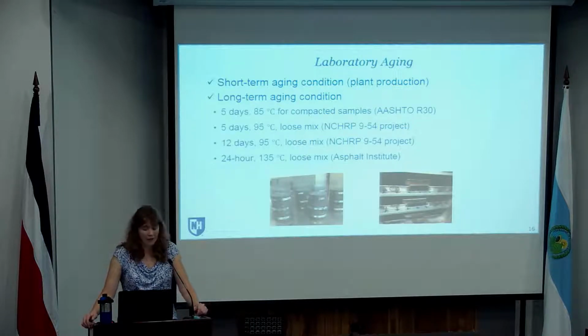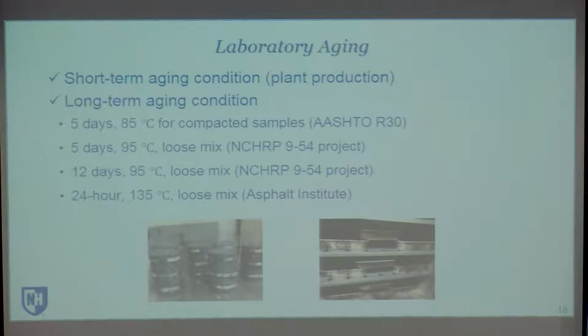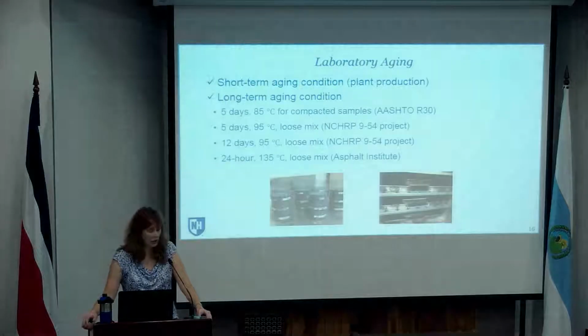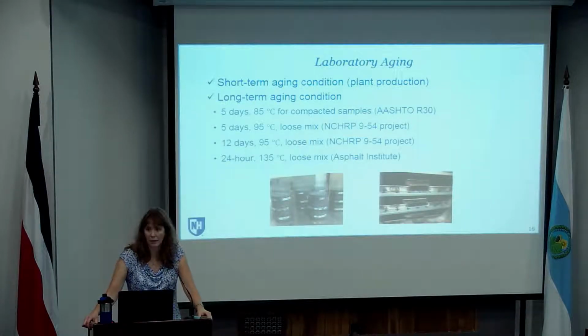So we looked at 5 days at 85 degrees C for compacted samples, which is the current recommendation through AASHTO R30. We're looking at both the 5 and 12-day 95 degrees C on the loose mix, which is coming out of the NCHRP 9-54 project that was recently completed. And then we also looked at 24 hours at 135 degrees aging on the loose mix that was coming out of Asphalt Institute recommendations. So we wanted to evaluate these different approaches to see if there are similarities or differences in terms of the properties that we're measuring.